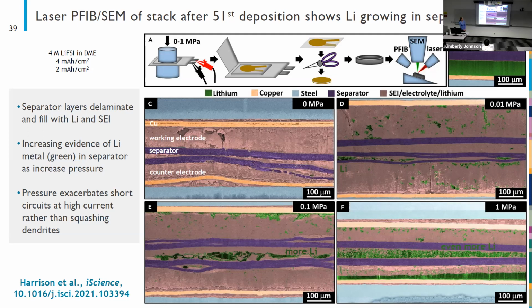Yes, they are. And I took this out of the talk, but we've also specifically looked at how the thickness changes and what impacts that has on energy density. I didn't talk about that today, but I think that that's really interesting. And you'll also notice that these 3 images, they don't have any lithium left at the counter electrode. That's actually consistent with the electrochemistry because we ran out of lithium and we were starting to reduce the capacity. In that 1 megapascal cell, that was the only one that was still delivering capacity at the end of the 50 cycles. And it's the only one where we have lithium inventory left in the cell.